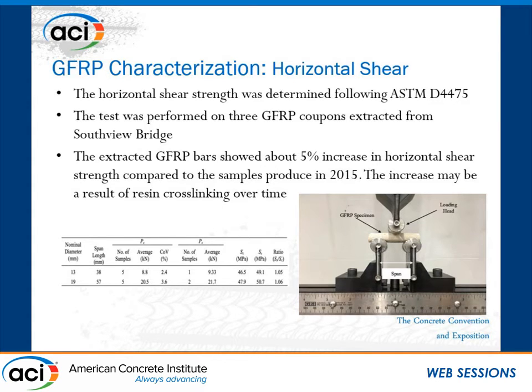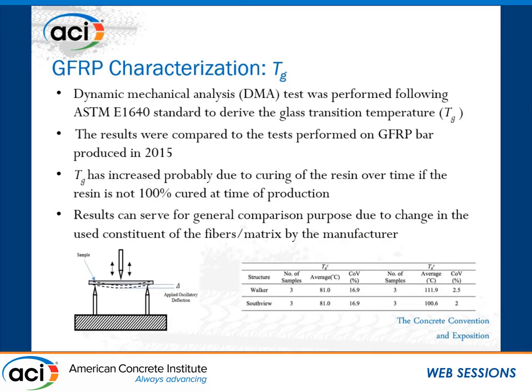So again, I need to mention that maybe this 5% increase is not a real increase, because we are not comparing apple to apple exactly. But the least we can say is that for sure there was no degradation, and the property was in the same range. The next test we performed was dynamic mechanical analysis, DMA, to investigate the glass transition temperature.